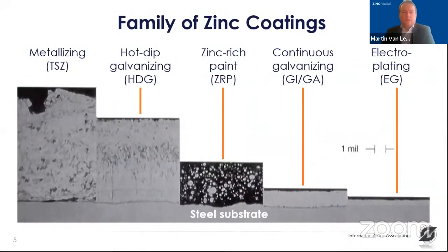So what is the family of zinc coatings? What kind of zinc coatings do we consider and do we have? First of all, at the left side of this picture, you see the thermal sprayed zinc coatings, also called metallizing. These coatings are typically applied as thickest coatings in the whole range. You would find typically coating thicknesses between 100 and 250 micrometers.